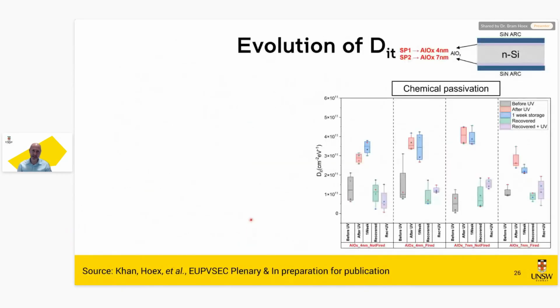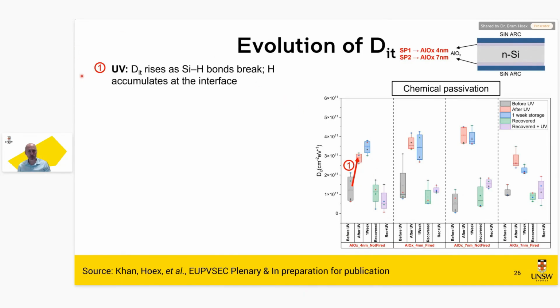So now we come to the very technical results, and this is something most companies would not have in-house to measure: the interface defect density as a function of treatment. I will guide you through it. First of all, on the UV exposure, we see a rapid increase of DIT for every sample. So these are the different samples, so not fired, two different thicknesses. The detail actually doesn't matter because they all show the same behavior. UV breaks silicon hydrogen bonds, which is one of the weakest bonds in the dielectric stack. And this hydrogen, I will show in the next slides, actually accumulates at the surface. So we break silicon hydrogen bonds throughout the stack, but the mobile hydrogen piles up at the interface.